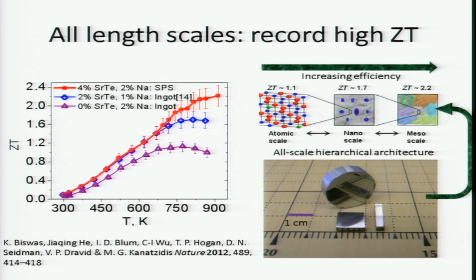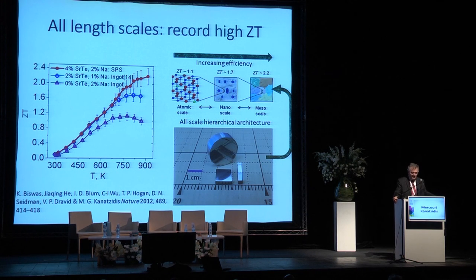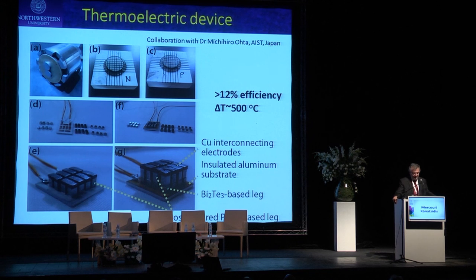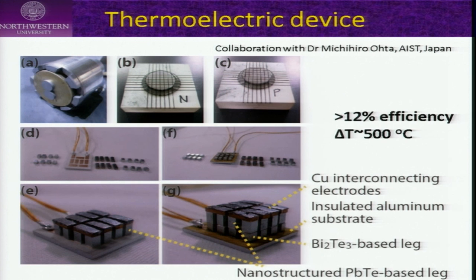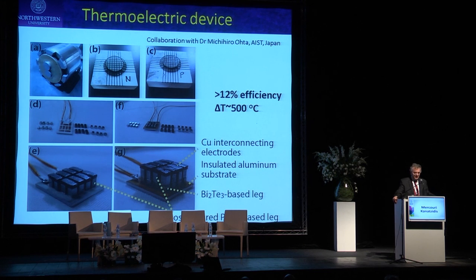So we've been working with our collaborators in Japan, Dr. Michihiro Ota, who has spent about a year and a half in my lab learning how to make these things. He's at AIST, it's a national lab in Tsukuba, Japan, and he has been making devices from this. So this is the first device made out of nanostructured material, and he was able to demonstrate over 12% efficiency with a hot side of close to 500 degrees C. So this is a delta T of about 500 degrees C. It's delivering 12% with a theoretical expected of close to 15%. So there's still some losses in the connections, both in the electrical and thermal connections of this.